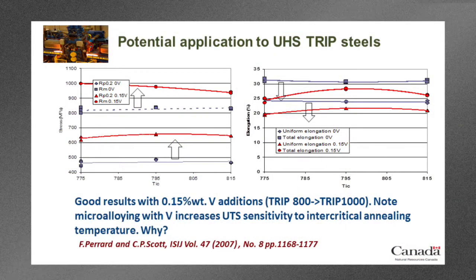So that's shown on this slide here. What you can see on the left-hand side, we're plotting yield strength and ultimate tensile strength as a function of the intercritical annealing temperature. That might seem a bit of an odd thing to do, but as I mentioned before, these steels are very heterogeneous sometimes, and they can be very sensitive to parameters like the intercritical annealing temperature. So that's why this graph is plotted in that way.